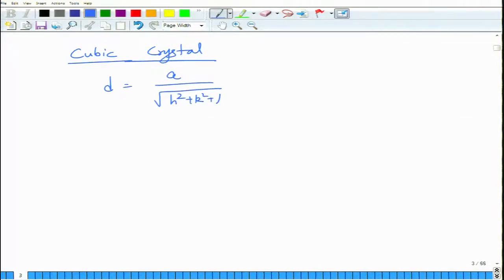And you can see now for crystals, we have let us say a cubic crystal. So for a cubic crystal, d will be equal to a divided by root of h square plus k square plus l square, all right. So n lambda will be equal to 2 into a divided by square root of h square plus k square plus l square, into sin theta. So you can see that your theta will depend only on square root of h square plus k square plus l square. So that is how you index your planes.